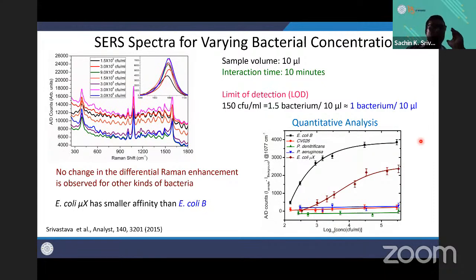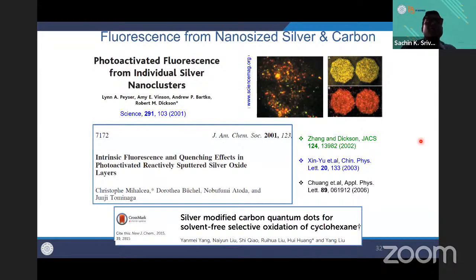We used it for enhancing fluorescence also, because of the 10 to the power 3 times enhanced field. What we saw is that silver nanoclusters show fluorescence, and not only that, carbon quantum dots also show fluorescence. I think this study was purely accidental. You make silver and silver starts giving fluorescence. How? Because it becomes silver oxide. They made silver quantum dots, and who thinks that silver gives fluorescence? I have a silver ring, it doesn't give any fluorescence. But you make a quantum dot and it starts fluorescing.